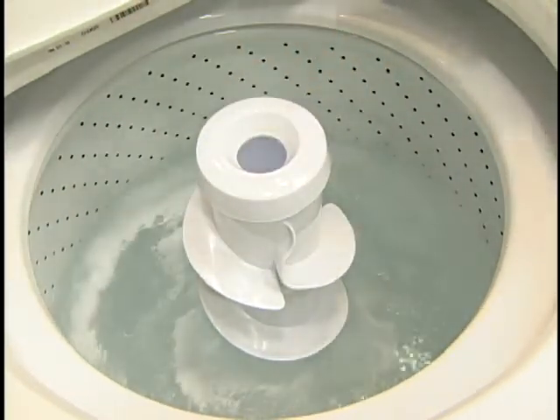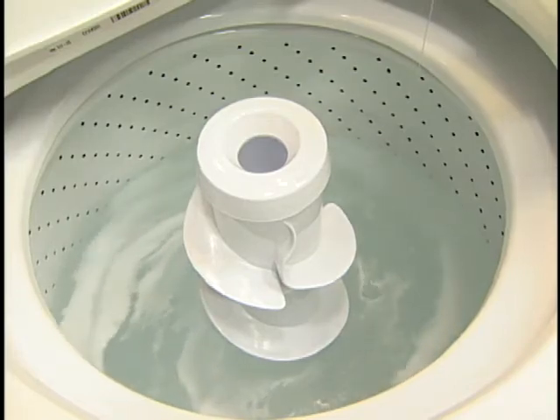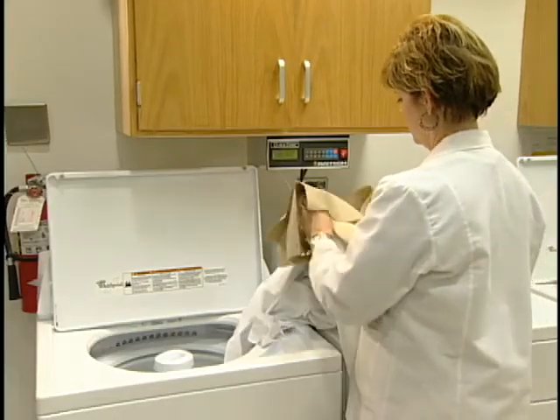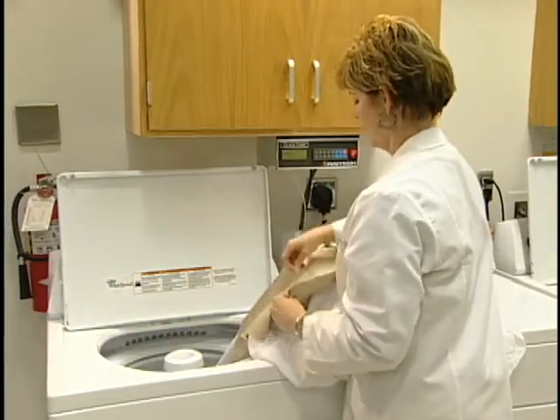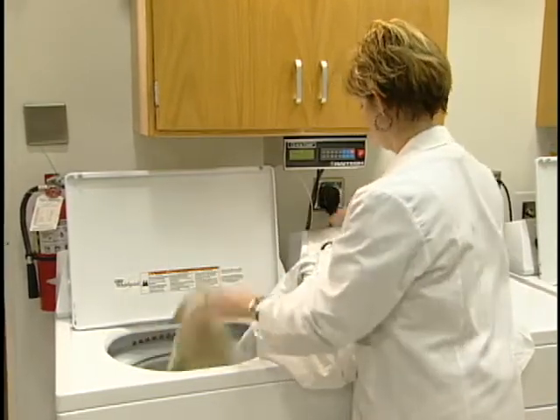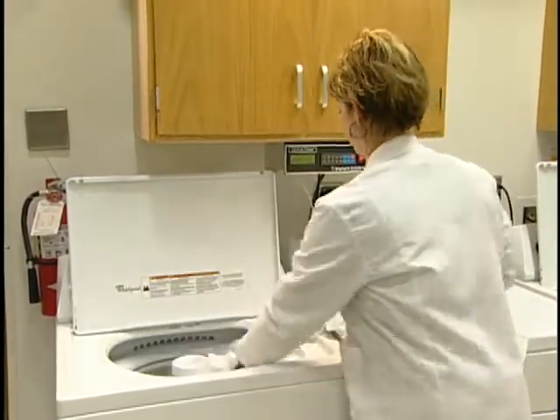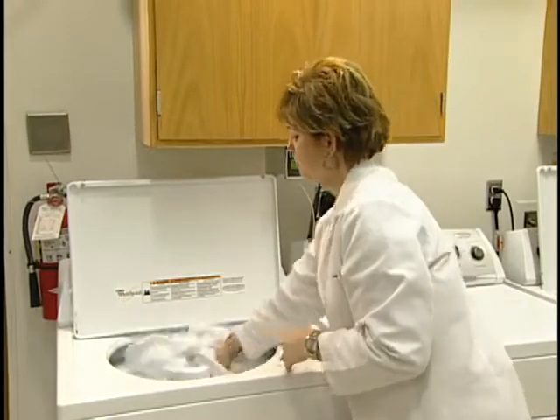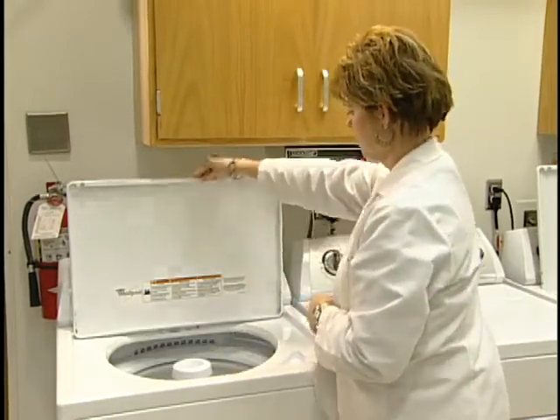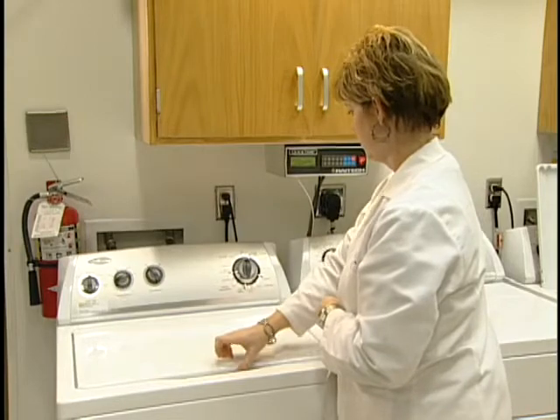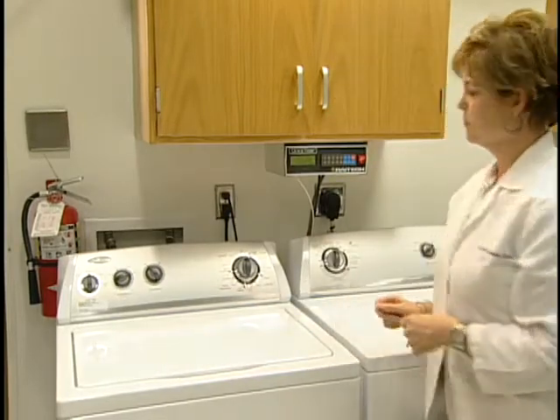The detergent is added while the washer is filled with water. After filling with water and adding the detergent, the specimens are added along with the proper ballast, as indicated by the test method. The ballast pieces are cut to a 36-inch square. The washing cycle is 12 minutes, followed by extraction, rinsing, and extraction.